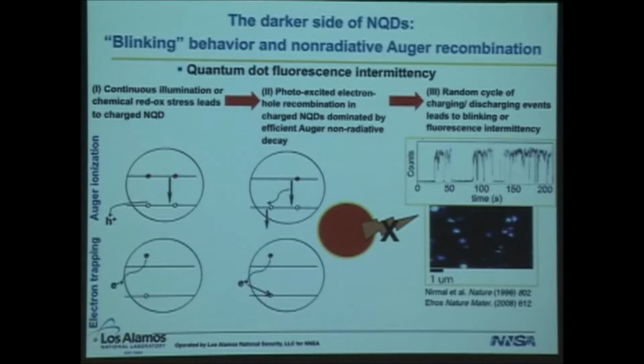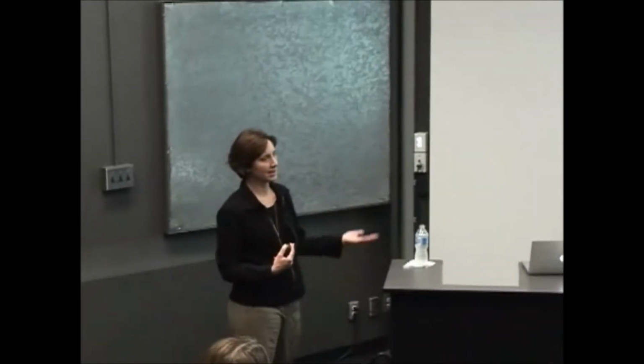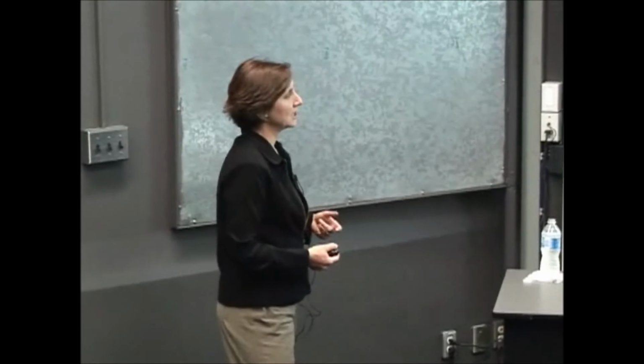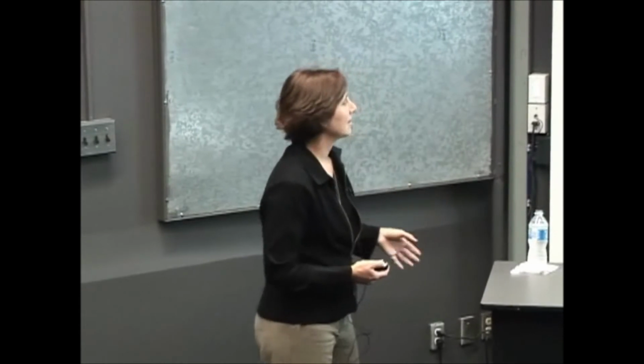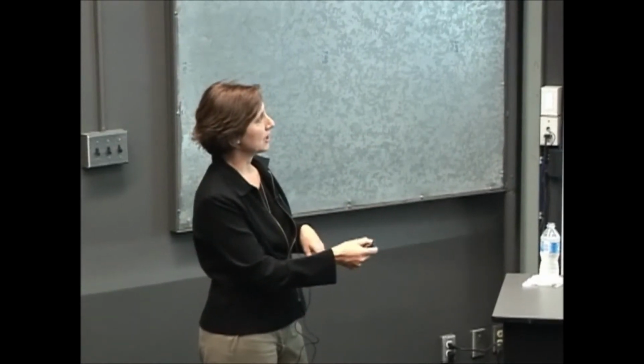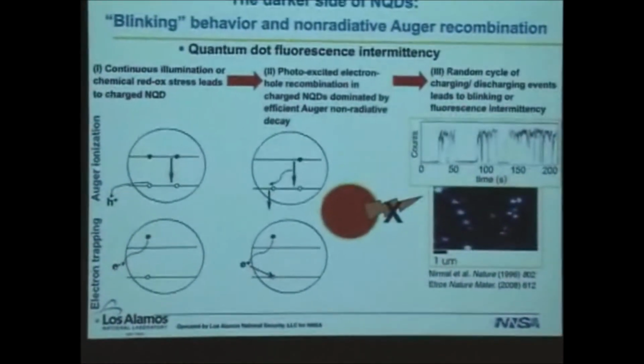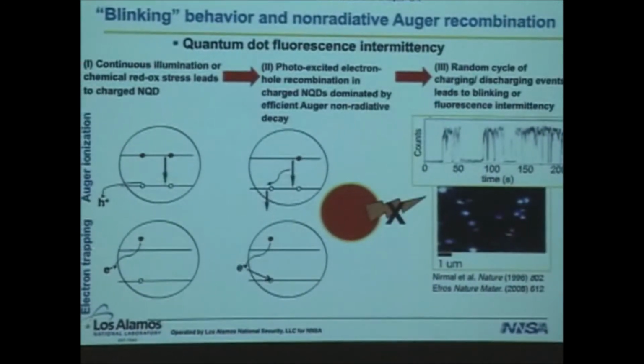Actually, more recently, we've developed a technique in SINT. It's a spectroelectrochemistry technique that is allowing us actually to controllably charge quantum dots and at the same time observe the emission from the quantum dots and obtain their lifetimes, and to really more definitively assess the blinking process and the mechanism there. I won't go into that in detail, but suffice it to say, what we found is that blinking actually results from two different mechanisms. This traditional mechanism associated with charging and Auger, but also simply hot electron capture to surface trap states that effectively short circuit the emission process as well.